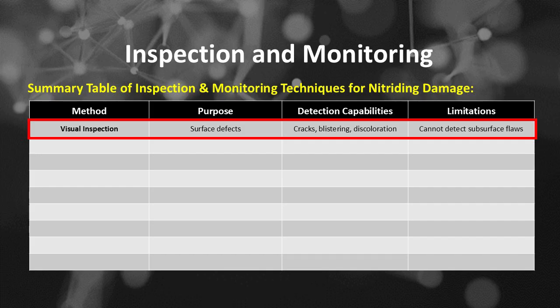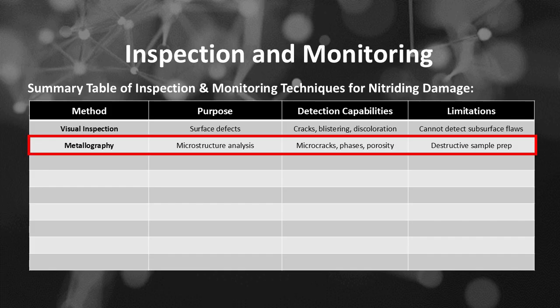If the method in use is visual inspection, its purpose is surface defects, its capability is to detect cracks, blistering, and discoloration, and the limitation is that it cannot detect subsurface flaws. If the method is metallography, its purpose is microstructure analysis, its capability is to detect microcracks, phases, and porosity, and the limitation is destructive sample preparation.